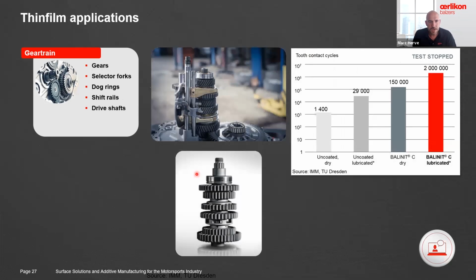If we look then to the gear train, this is where I'm going to answer the previous question about the hardness. When we do coating on gears, gearbox and the gears, it's a mix between shocks, rolling, sliding. There's a lot of different things happening on the gearbox. And here in this case, actually, harder is not better, because if you go with a too hard coating, it becomes brittle and basically can create cracks and get delamination.